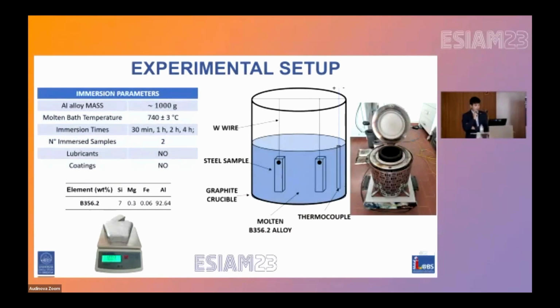The static immersion test apparatus involved the use of an electric furnace equipped with a graphite crucible. The aluminum alloy was a primary aluminum silicon 7 magnesium alloy with a low iron content. Approximately 1 kilogram of alloy was melted for each test and held at 740 degrees. A pair of samples of the same material were cleaned with acetone and then submerged in the liquid bath supported by tungsten wires. 4 different immersion times were chosen for the test, and once the samples were removed from the bath, the wires were cooled and the aluminum alloy was poured into a permanent mold.